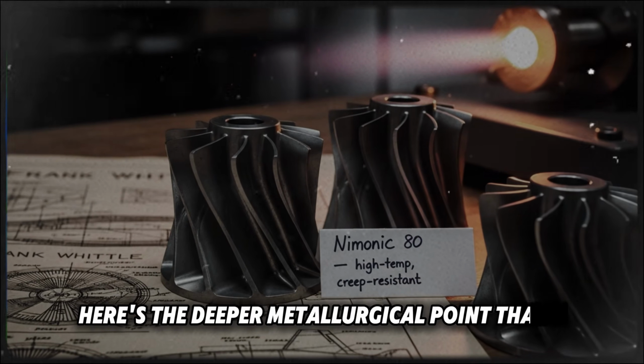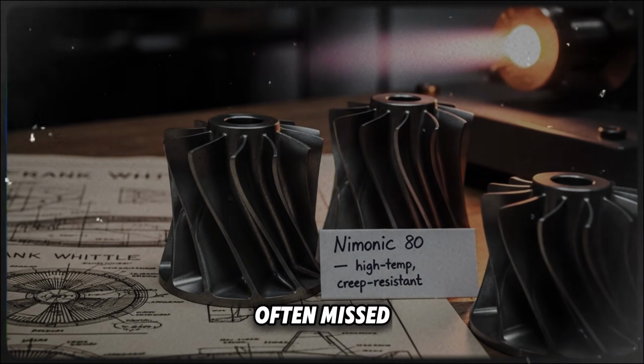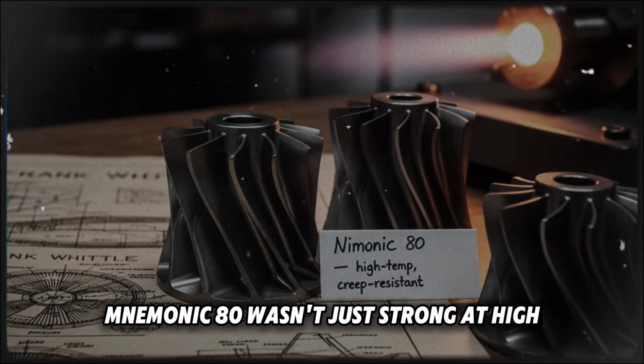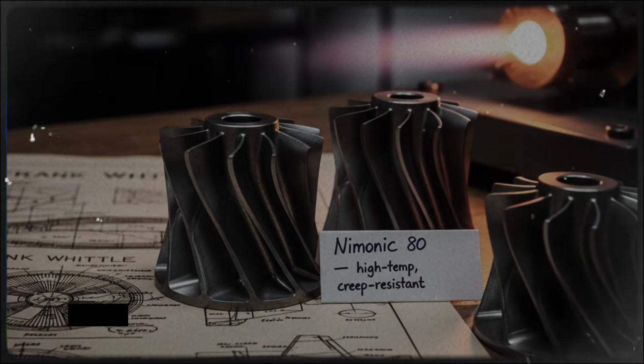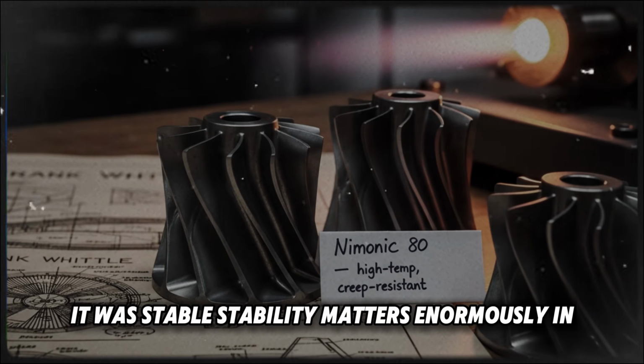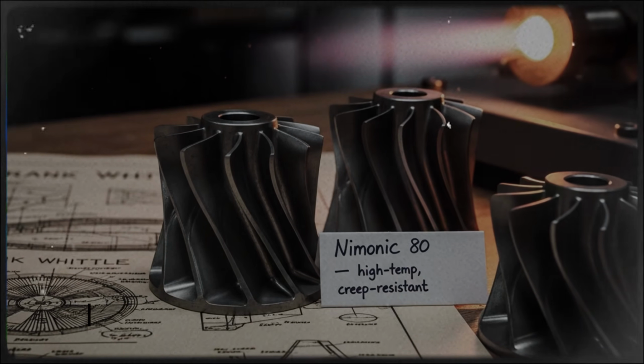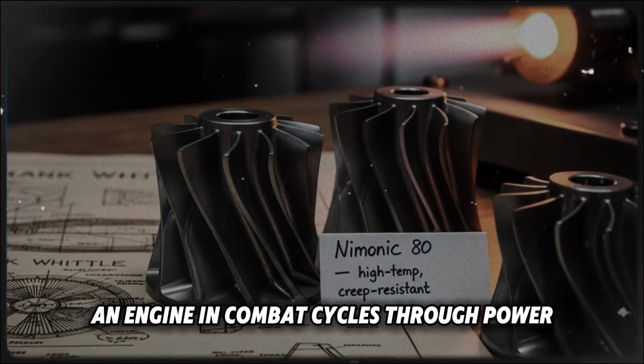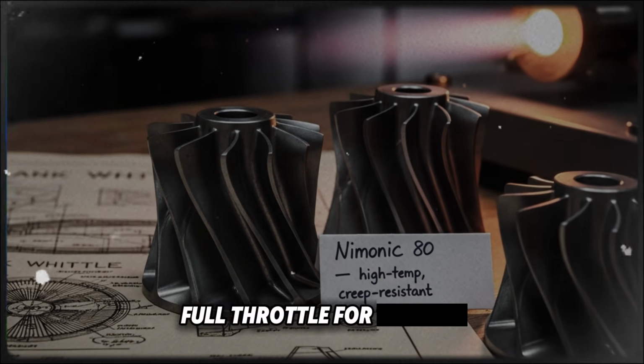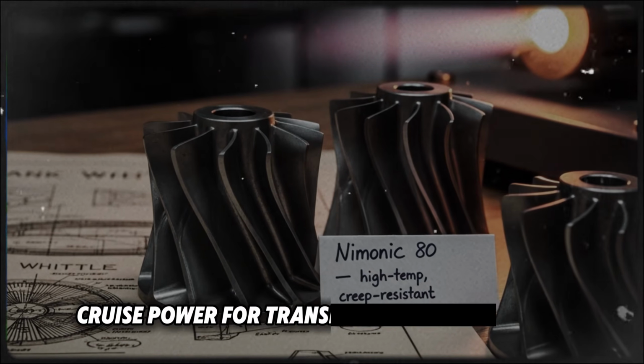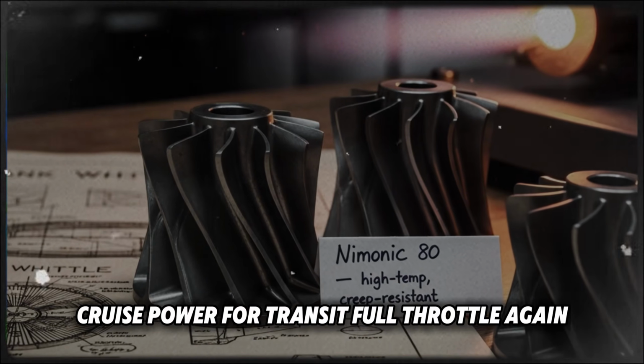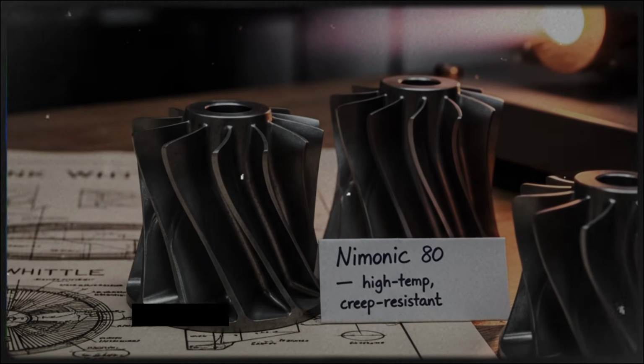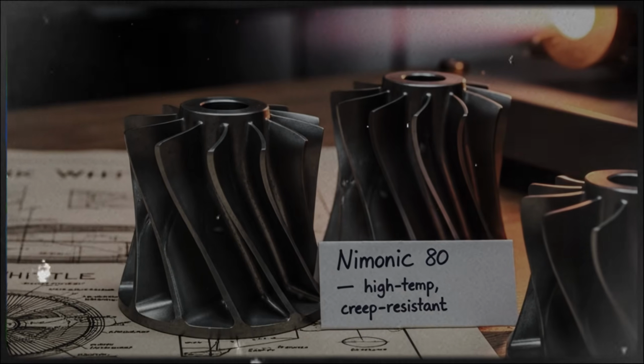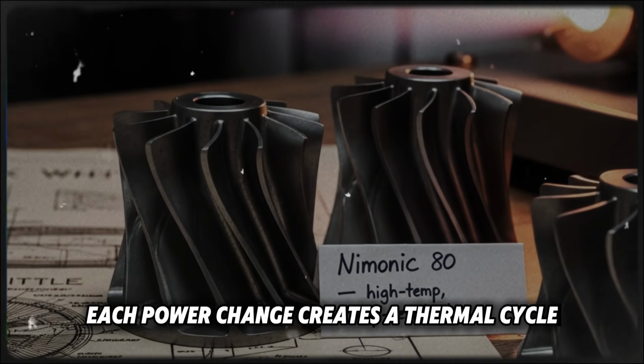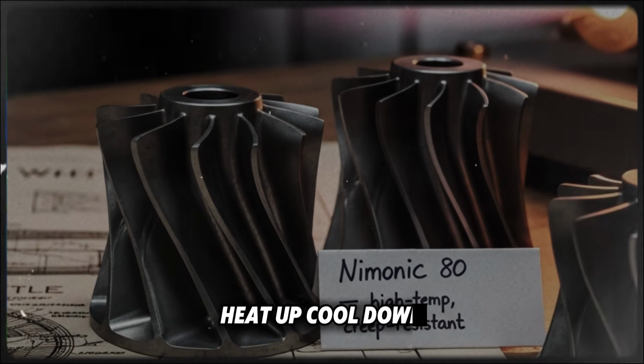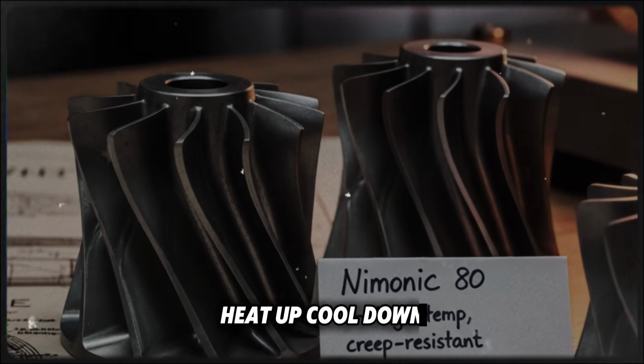Here's the deeper metallurgical point that's often missed. Nimonic 80 wasn't just strong at high temperatures. It was stable. Stability matters enormously in combat conditions. An engine in combat cycles through power settings rapidly. Full throttle for takeoff, cruise power for transit. Full throttle again for combat. Cruise power for the return flight. Each power change creates a thermal cycle. Heat up, cool down, heat up, cool down.